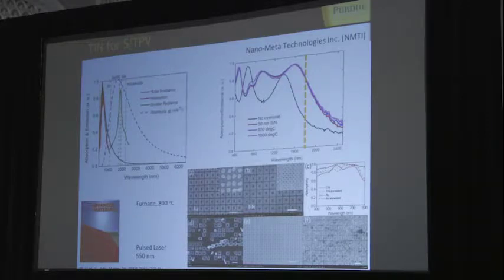So what we did is this broadband absorber, made by simple rectangular rings out of titanium nitride and out of gold, just for comparison. When you make it out of gold, you heat it up to 800 Celsius. That's what happens to gold. Of course, it's completely out of the game. And nothing happens to titanium nitride. And it does absorb almost independently of the angle of incidence and polarization in the whole spectrum of the sun.